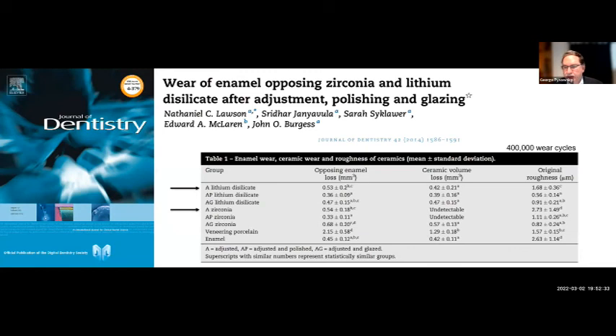And this is a study just showing some of the implications that can occur from those areas. What we have is, let's look at the opposing wear of what happens if we have a rough surface opposing the wear of a tooth structure. So here in the first line item, we have an adjusted lithium disilicate. And then we have a polished surface of lithium disilicate. And then we have a glazed surface of lithium disilicate. So in the lithium disilicates, if you adjust it and just put it in the mouth, you create the roughest pattern of wear to the opposing tooth structures. It can be very catastrophic. If you polish it, you basically cut it in half. So polishing is a very significant factor.